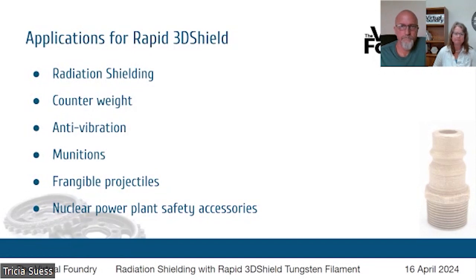And we're seeing shielding reductions of about 90%. We base all our calculations on cobalt 60, but I think the best we ever saw was about 140 rem per hour down to about 7. So it worked very well. Obviously it wasn't cobalt 60 there, but we're not going to argue with the results. We've had pretty good success with it.